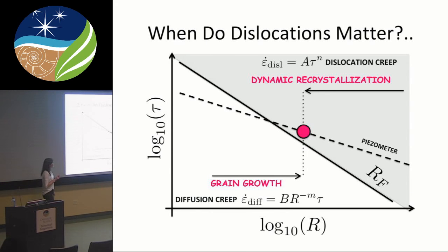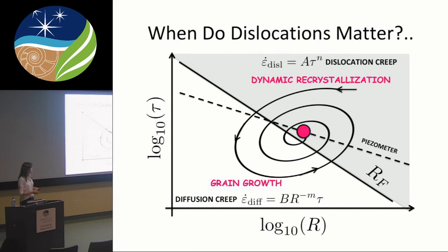Actually, before I get to the earthquake cycle, again, the reason we care about grain size is because it tells us something about the strength of rocks. Before I said how the piezometers we get from looking at the rate of recrystallization and rate of grain growth, and at some point they reach the steady state. The fact that the path towards the steady state can be somewhat complicated and includes oscillations, now we're thinking something like this may be happening, where as you're recrystallizing, you're oscillating, and so you're weakening and strengthening the material in cycles, and you're traversing this map where you deform by dislocation and diffusion creep as your material goes towards the steady state.